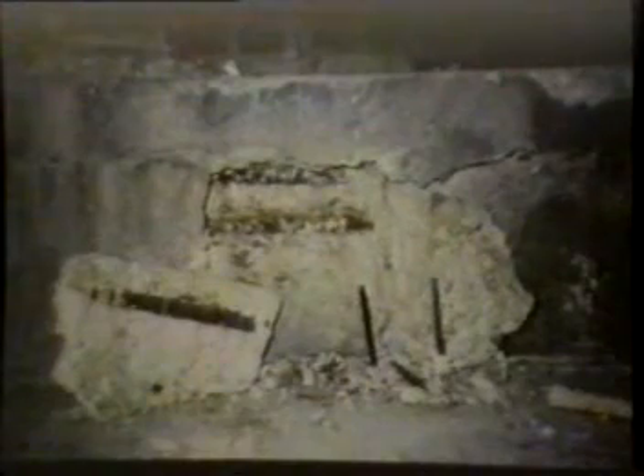So you can do a delamination survey, and you think you've got a reasonable area for repair, and you go out and you start chipping, and you follow the corroded bars, and your areas might double. Something very important here. If you're an engineer doing the survey or you're a contractor bidding on this work, you really need to understand what type of problems you have. Maybe a pilot test may be appropriate.